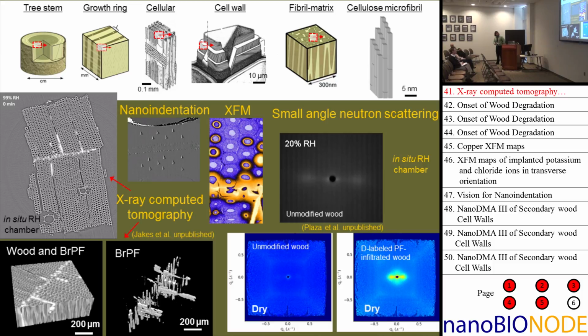And indeed, what we did was, we took a really low molecular weight phenol-formaldehyde adhesive that we labeled with deuterium, and then we put that in the wood structure. And what we saw was that on unmodified wood dry, you don't see these peaks that correspond to these cellulose microfibrils, but with the deuterium-labeled phenol-formaldehyde adhesive, you do see these peaks.